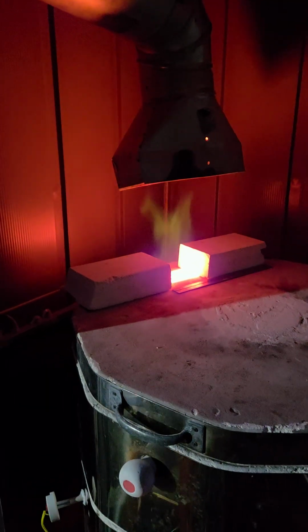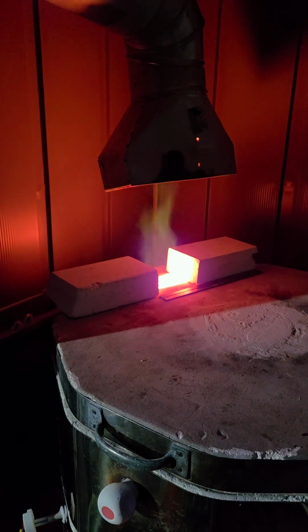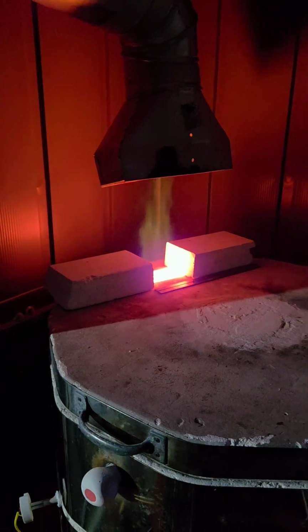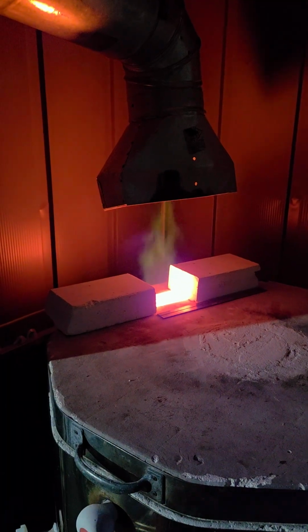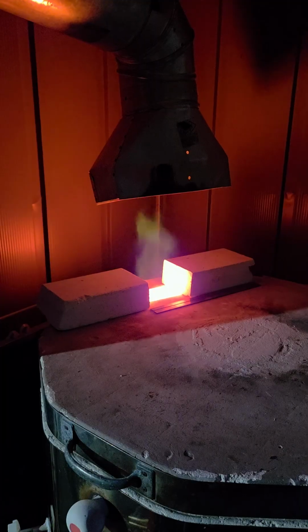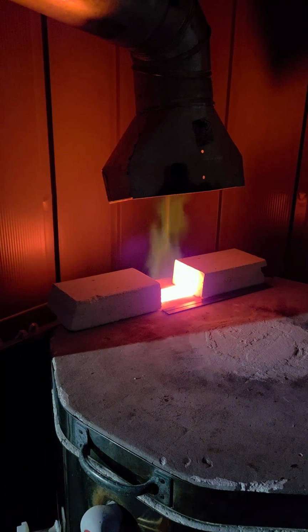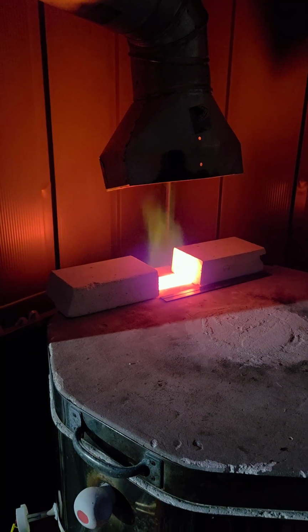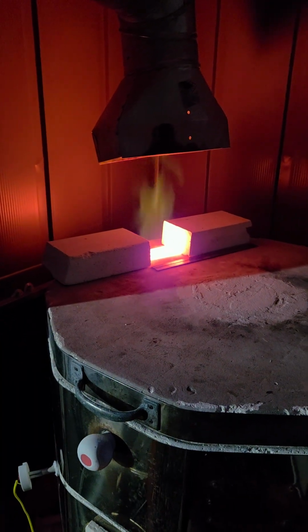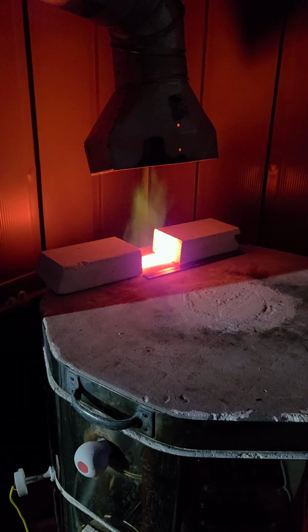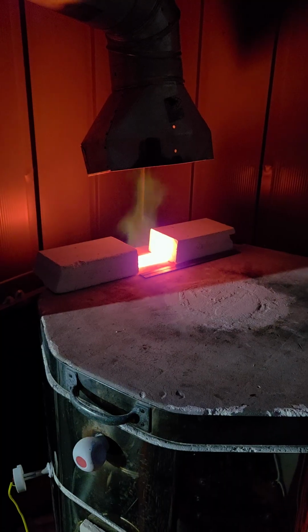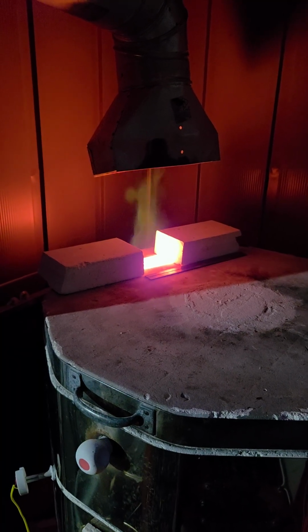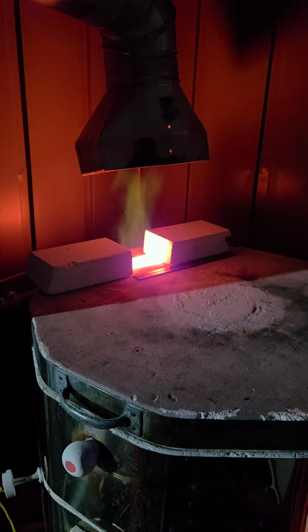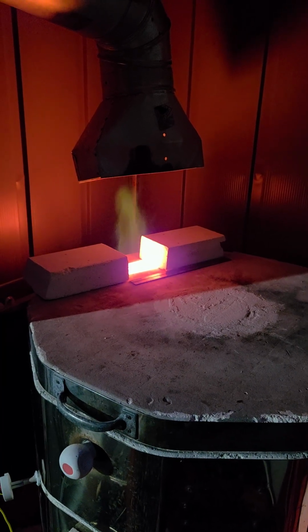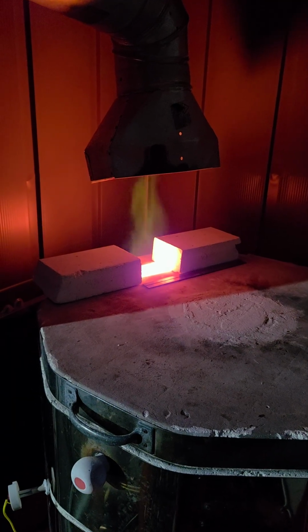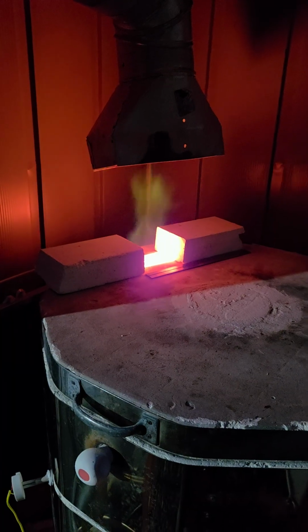So I'm not going to make any adjustments because this will continue to slow down, and it just seems to work to shoot for about 60 degrees per hour during that last 60 up to about 100 degrees of temperature change. Typically my pyrometer reads about 1277 when cone 10 goes down. The book says 1282, but I always figure that 1277 is about that time, and I'll start looking at the cones around 1240, 1245, because that's usually when cone 9 begins to go down.